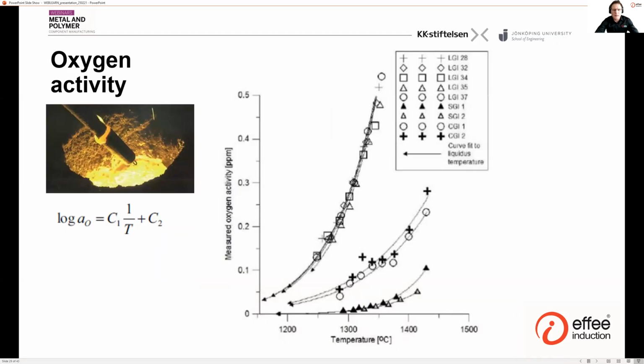So the oxygen in the melt can be measured using something called oxygen activity measurements, and it's a probe that you put into the melt, and the reading you get is called oxygen activity, and it's extremely temperature dependent, according to this formula on the left here. And in the diagram you can see the measured oxygen activity for different cast iron versions. So we have the ductile iron in the bottom, the compacted graphite iron, and then the lamellar graphite iron to the top left in the diagram. So we get definitely different measured oxygen levels in the different types of iron. We can take the next